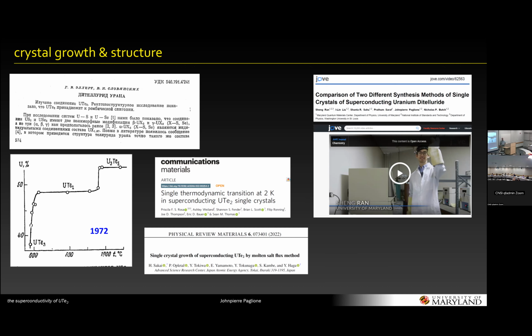Yes, Chris, and then Steve. Tellurium is going to have a very high vapor pressure. So is this really an effect of how much overpressure you have of tellurium, and you can shift these phases by just how much? Yeah, that's what we thought, and we tried to do a high pressure growth, but that didn't quite work. This is a strange aspect of this material. So you can grow UTe2 in a flux of tellurium, a tellurium-rich solvent, a crucible with 10 times tellurium to uranium, and you get crystals that are not superconducting at all. You would think that would be the ideal condition to reach the stoichiometry. And in fact, if you grow with vapor transport, if you reduce the temperature of growth, you get higher TC crystals. So it's everything the same, you just turn the knob and the TC goes up.